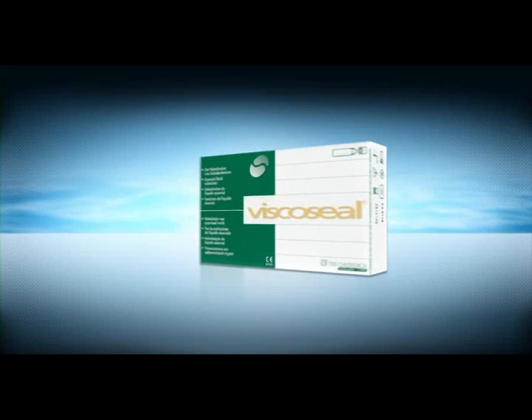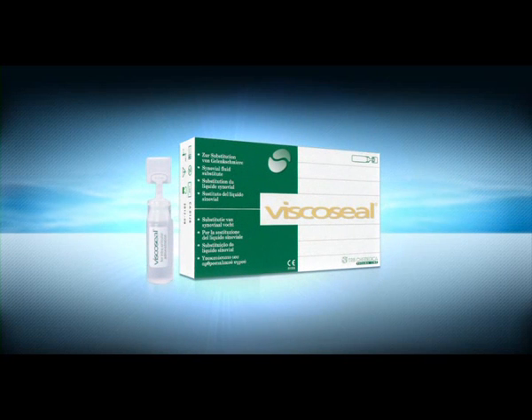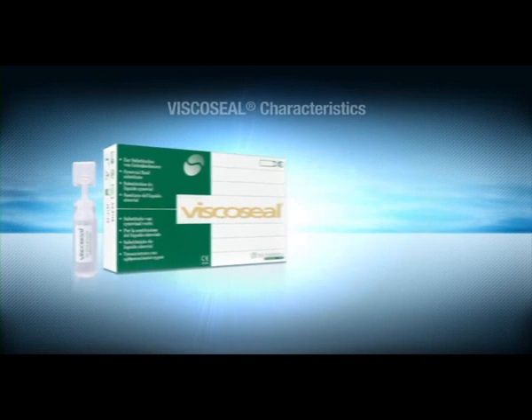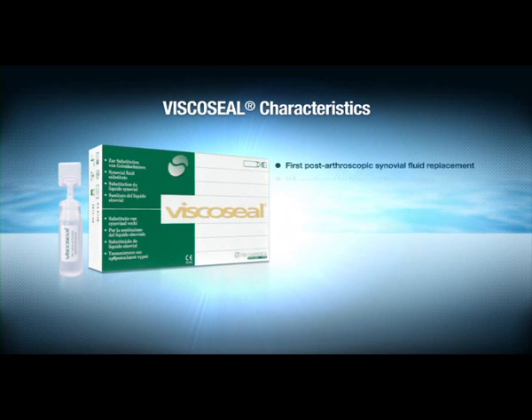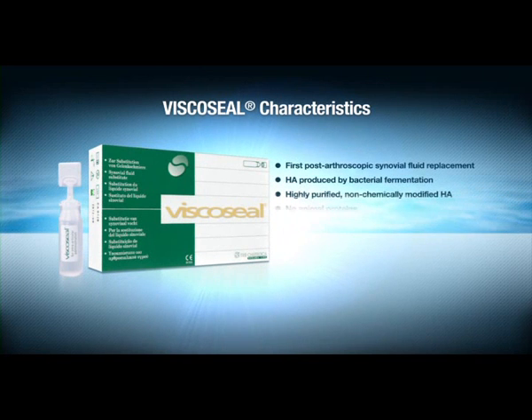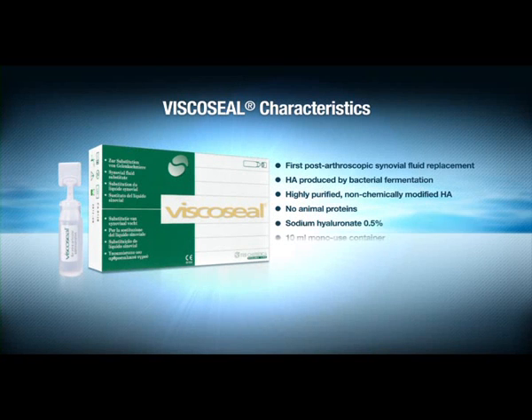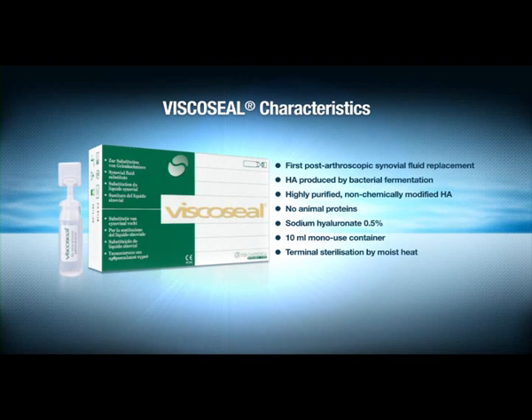Viscoseal is the first post-arthroscopic synovial fluid replacement. It contains highly purified, non-chemically modified sodium hyaluronate, produced by fermentation. That is, it is devoid of animal proteins. It contains 10 milliliters of a 0.5% solution of HA, which is close to the concentration in normal synovial fluid.